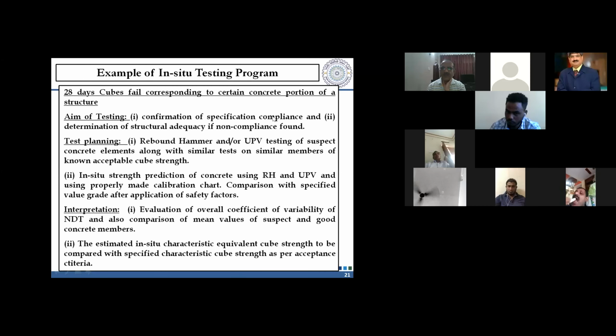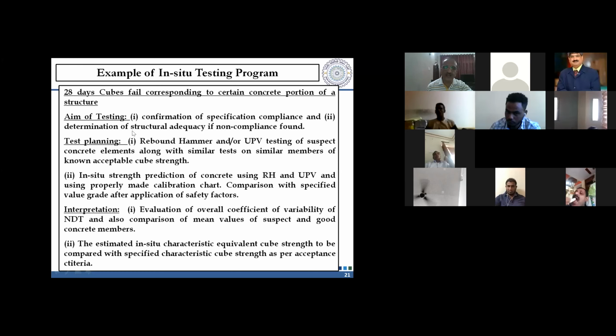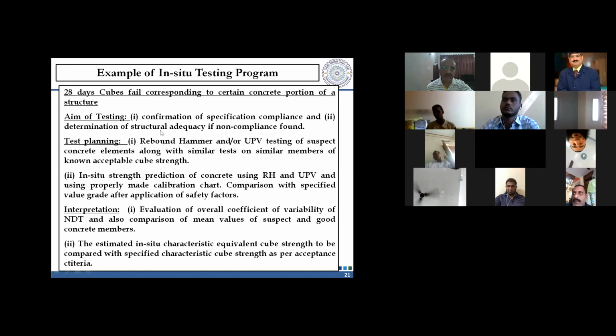If, after doing NDT, you really find that it is not complying, you will not straightaway say that it should be demolished. By using that reduced grade, the lower strength which you are now finding, you will find out the structural capacity. You can then carry out structural analysis. If that is coming out to be okay, then you can go ahead with that. The problem is only to that extent in a certain portion. If after finding out structural adequacy you see that things are still bad, then you have to take a decision about repair, restoration, or demolition, depending upon the case. This is about the aim.